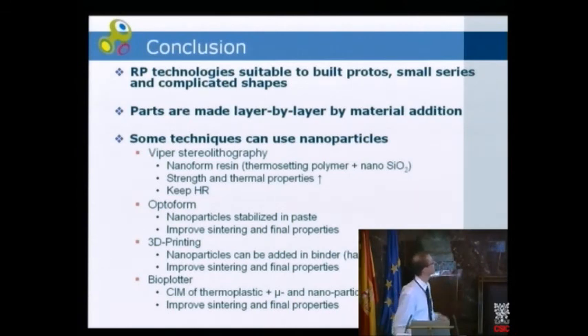So with the Viper stereolithography technique, we have Nanoform resins, which are a blend of thermosetting polymers with nanoparticles of silicon oxide. And we can keep the high resolution mode of the stereolithography. We can build very detailed parts with improved strength and thermal properties higher than current resins. With Optoform technology, we can add nanoparticles inside the paste. They are stabilized inside the paste. There is no settling inside the paste. And the nanoparticles will improve the final step of sintering and the final properties of the part. We can add nanoparticles to have very particular properties in the final part.